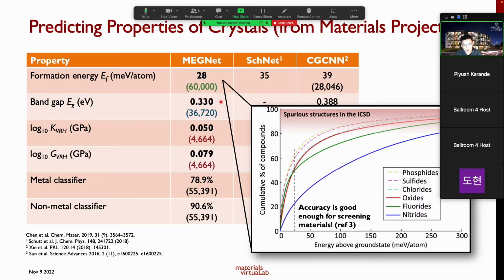Now, if you look at the band gap predictions, we get about 0.33 eV, which is also quite good. And then we also have things like the bulk and shear modulus, which are on par with the state of the art. Okay. Now, one of the problems with MEGNet models, however, or with graph neural networks in general, is that they tend to be very data hungry. Okay, and you notice that in terms of data set sizes, we have very, very different data set sizes, right? So that can be a challenge for some of the model accuracies.